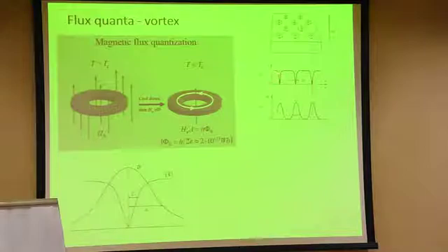The dropping to 0 happens over a distance of 2 coherence lengths. At the same time, the internal magnetic field has to be 0 in the superconducting region between vortices, and it has a maximum at the center of the vortex core.